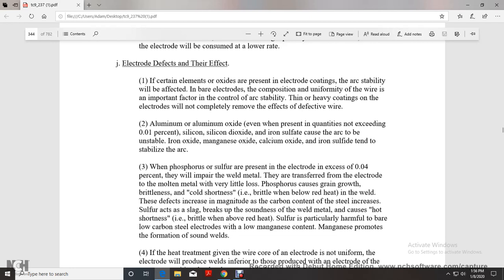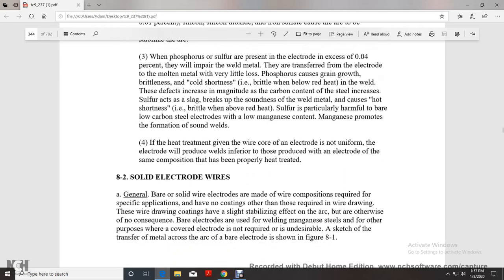Phosphorus and sulfur present in the electrode in excess of 0.04% will impair the weld metal, with the transfer of the electrode with the molten metal with very little loss. Phosphorus causes grain growth, brittleness, cold shortness, brittle below the red heat, and in the weld, the defect increases with the magnitude of the carbon content in the steel. Sulfur acts as slag, breaks up the soundness of the welded metal, and causes hot shortness, brittle above the red heat. Sulfur is particularly harmful to bare low carbon steel electrodes with low manganese content. Manganese promotes the formation of sound welds.